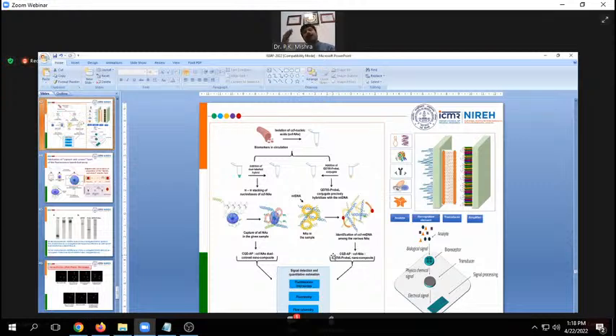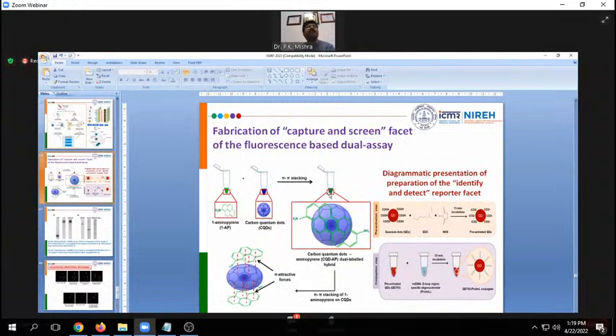And we had a different nanoanalytical framework, which was of quantum dot, labeled with the bioprobe. The bioprobe was labeled with a fluorochrome, and these quantum dots were 705 nanometers in excitation emission spectra. So to recognize the whole DNA, there was a green fluorescence pattern, and for the mitochondrial DNA that we isolated from the child, we had a red fluorescence spectrum. So green versus red. Fabrication of the capture and screen facet of the fluorescence-based dual assay took place, wherein we allowed the pi stacking to take place, and then carbon quantum dots were labeled with aminopyrene.